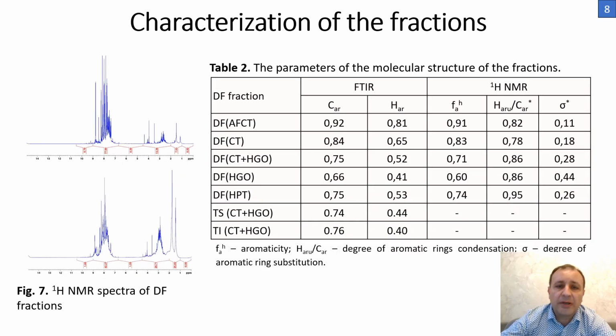The nuclear magnetic resonance spectra show strong signals in the spectral region of 9.5 to 6.7 ppm related to aromatic protons and weak signals from aliphatic protons. The molecular indices estimated from Fourier transform infrared spectroscopy and nuclear magnetic resonance spectra are shown in table 2. The data confirmed that all fractions consist predominantly of aromatic compounds.